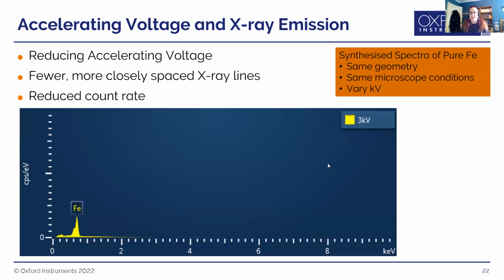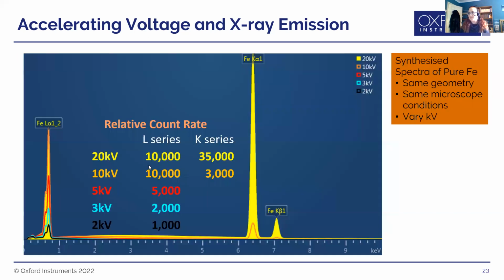And by the time you get down to 3 kV, even your low energy X-ray line is quite reduced. This means you need a really sensitive detector in order to pick these up and make the best of the signal coming from your sample.